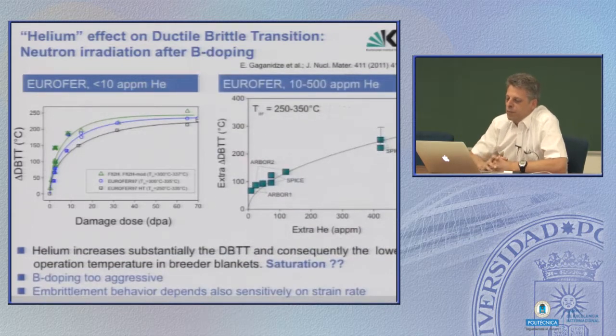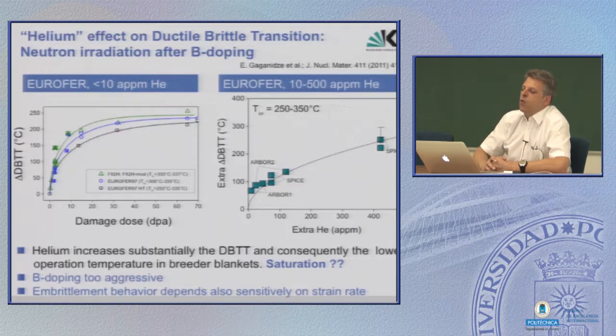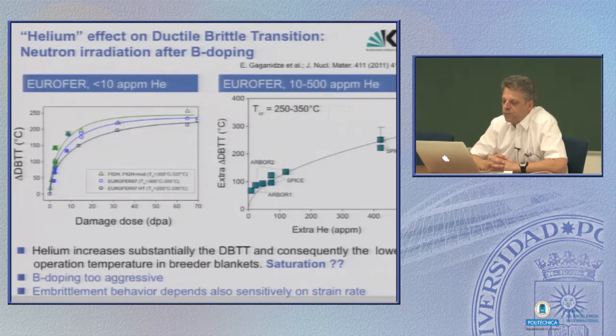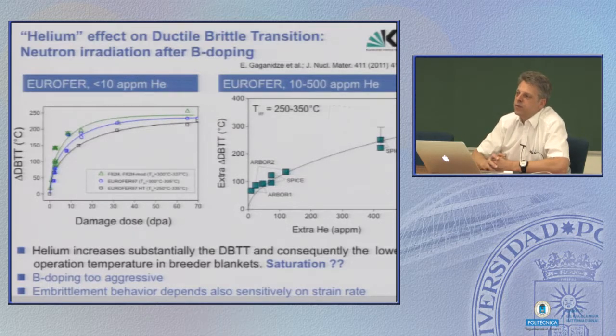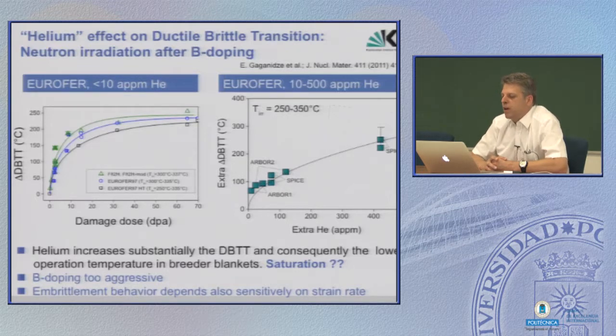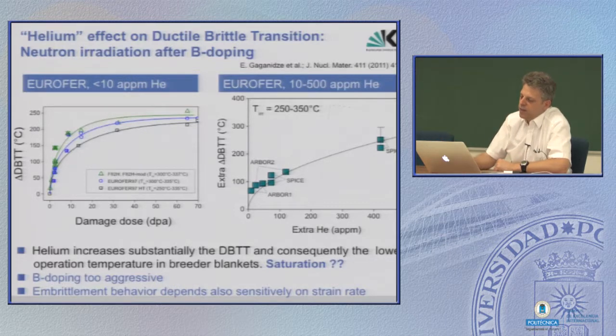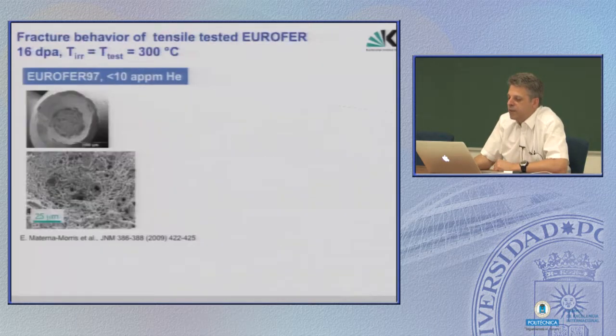What has been done is boron doping. Another option would be to use a very expensive isotope, iron 54. So far nobody could afford this test in a huge amount. So what we have are really only these results without helium transmutation and with helium artificially produced by transmutation in a reactor. From this we at least have maybe overestimated and therefore very conservative estimates of the helium effect. And from what we know today, the limits are at or around 500 appm helium.